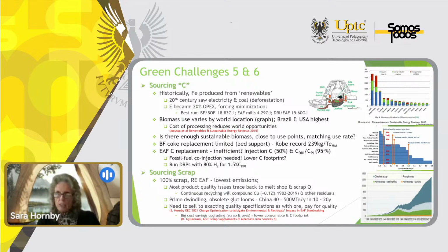As in terms of the blast furnace, we can only substitute a certain amount of coke for biomass in the blast furnace because we need the coke to sustain the charge that's put to the furnace, the lowest of which has been achieved by Kobe Steel with a record of 239 kilograms per ton of hot metal. Now, the arc furnace carbon replacement is possible, but it might be inefficient because with injection of carbon to date, 50% efficiency has been achieved on average, whereas using pig iron or DRI with carbon in situ gives us a 90%, 95% or more efficiency on the carbon molecules held within.